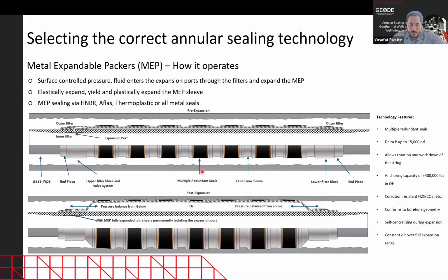When this technology was tested to geothermal temperatures, it has multiple sealing elements, and each one is a redundant element. So one seal making full contact will be able to withstand the delta pressure that we need. But in this case, you have multiple of these seals as redundancy, especially in open hole applications where you need redundancy. For geothermal applications, it's been qualified to 6,000 psi delta P, and for other applications, it can go up to 15,000. So it's a very unique technology that can be utilized in geothermal wells, either in combination with cement or in lieu of cement, just providing open hole isolation.